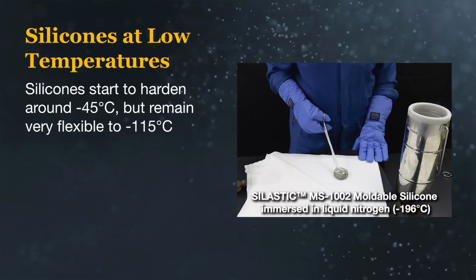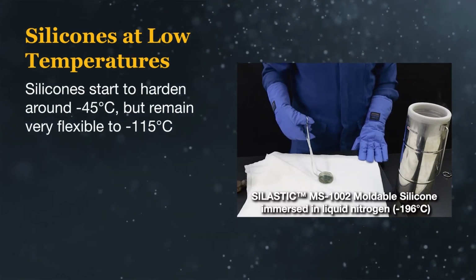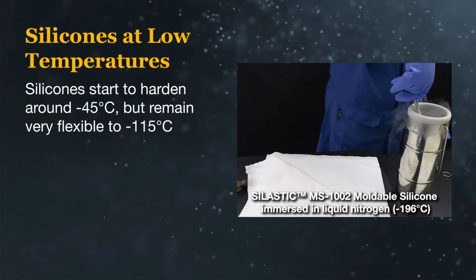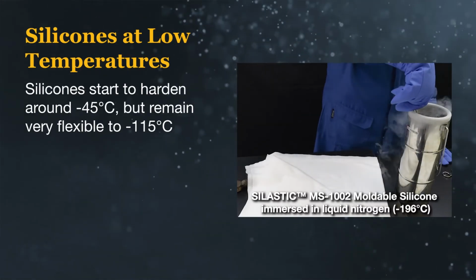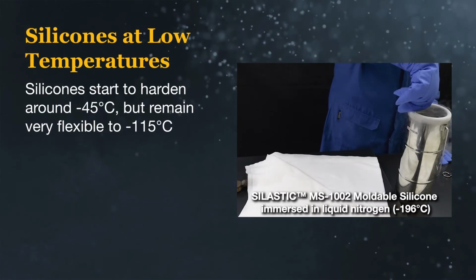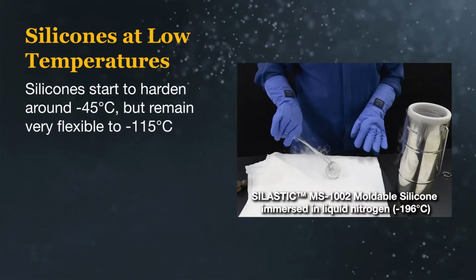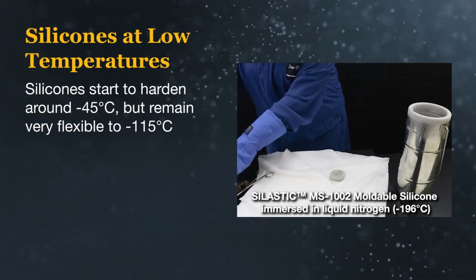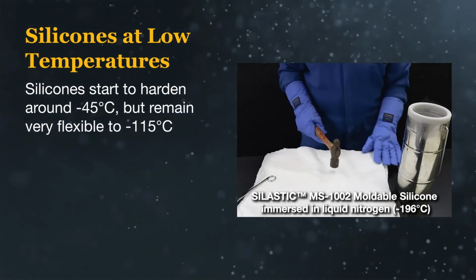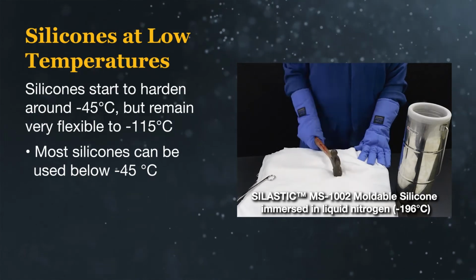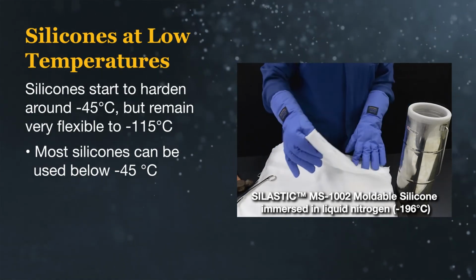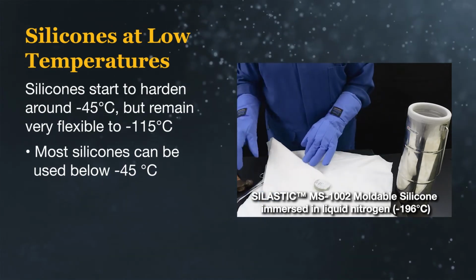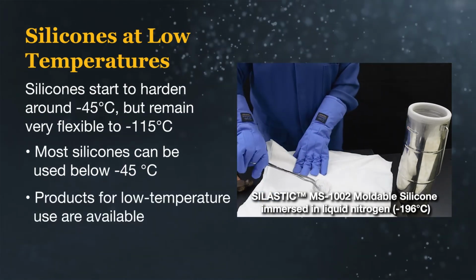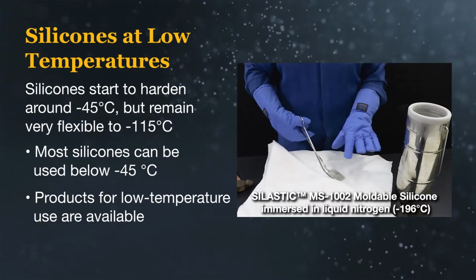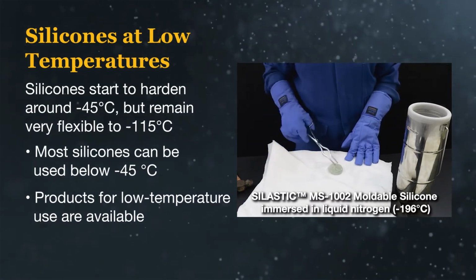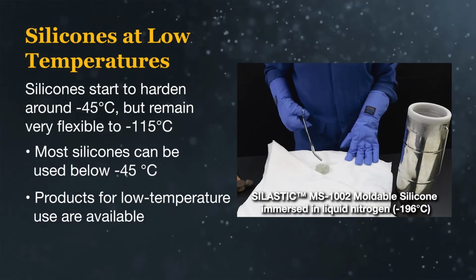While the true TG is around -115°C, most silicones turn from soft rubbers into harder rubbers around -45°C. This is commonly mistaken as the glass transition temperature. Although silicone gels will become somewhat brittle at this temperature, all other silicones just become harder rubbers. Many customers can continue to use standard silicones even below -45°C, since they remain elastomeric and stretchy. Dow makes special silicones that can be used below -45°C without showing the stiffening. You can find low temperature capable offerings in our product selector guide.